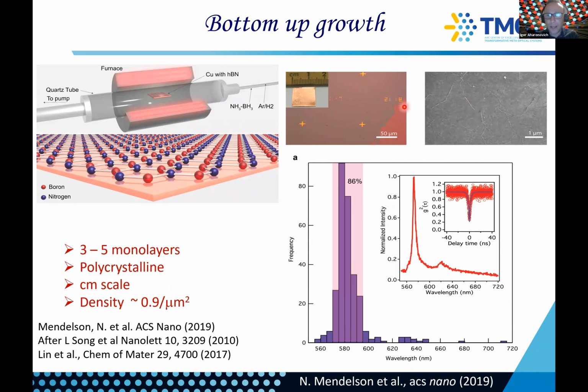It's a very bad quality material. So the material itself is bad. It's very polycrystalline. You can see it here. But nevertheless, the good part is that we can have emitters that are localized around 580 nanometers, and most of them are actually appearing in exactly this region.